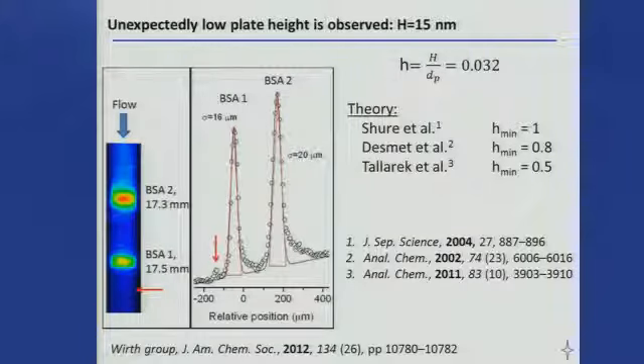And the plate height for a protein is normally about 8 microns, the best you can do. And these things came out to be almost 3 orders of magnitude better. And there's something called the reduced plate height that a lot of people use, which is, okay, you're going to improve the plate height, as I said earlier, with smaller particle diameter, but it's predictable how well you'll do. So if you divide your plate height by the particle diameter, back then it was thought this could never be less than unity, and we saw 0.03. And what that meant was that we couldn't possibly publish this work. It was just way too far from what was possible.